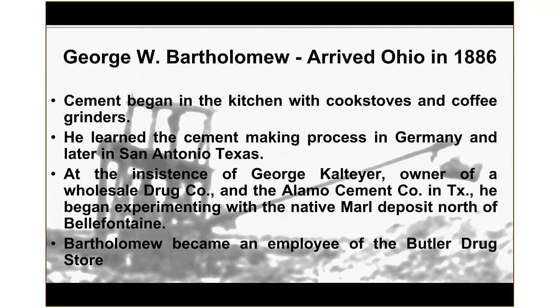And so the cement was being produced by drag lining this marl, which is a calcium carbonate rich mud. And so when we produce Portland cement nowadays, we use a source of limestone, and we use a source of silica and a source of iron as a flux to produce Portland cement. And so these native marl deposits had a fairly perfect raw ingredient list that allowed this material to be fired in a kiln and produce Portland cement, not too unlike what we see today.